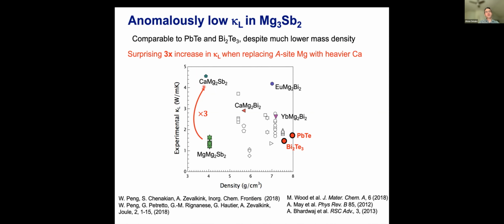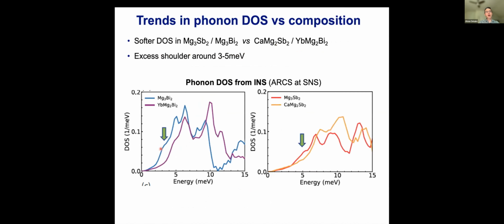And so we started with some powder inelastic neutron scattering measurements to look at the phonon DOS, and we see that indeed when we replace magnesium with calcium in the magnesium antimonide, or magnesium replaced with ytterbium in the magnesium bismuthide here, we systematically see, so going to the heavier element, we see a softening of the low energy part of the phonon density of states, which is quite strange.